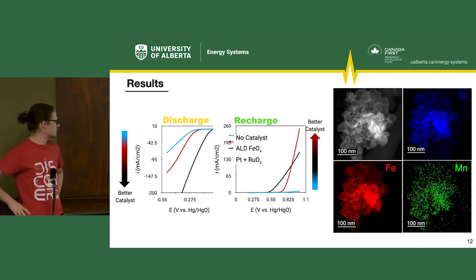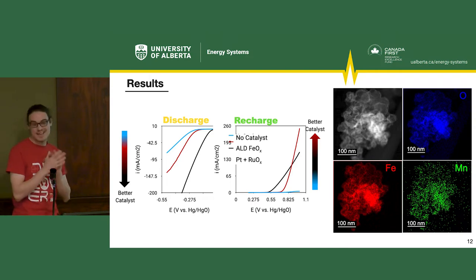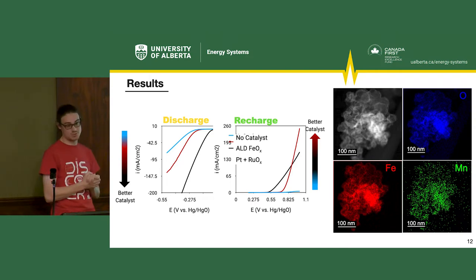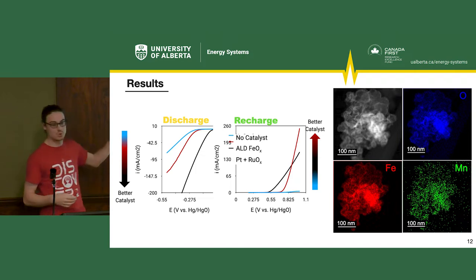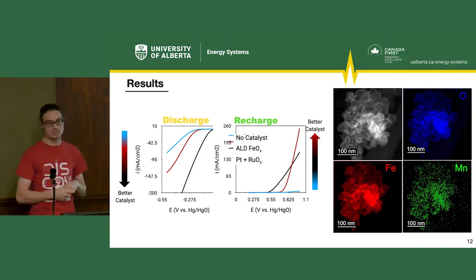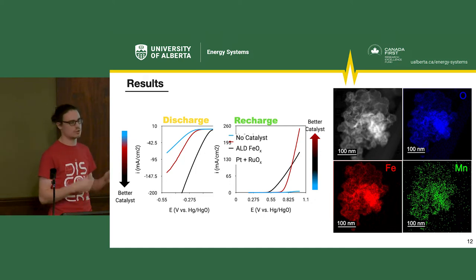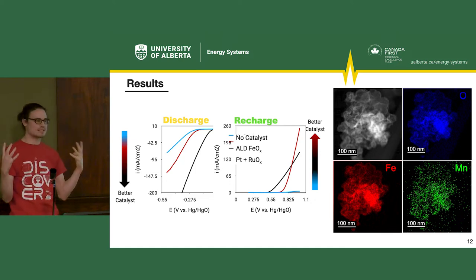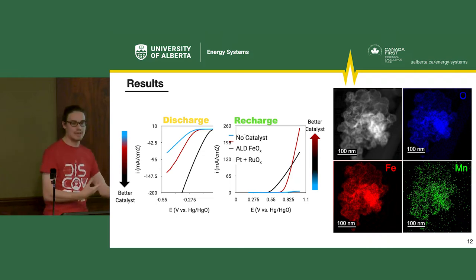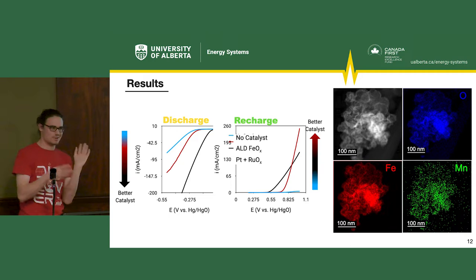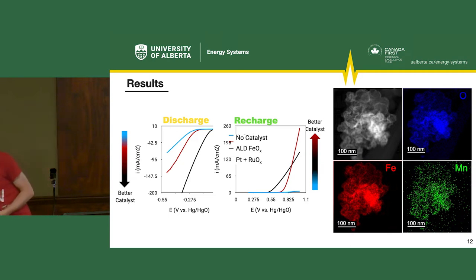So discharge could be improved. Well, it just so happens that the manganese oxide I'm using actually is a catalyst towards the discharge reaction. Somebody before me was doing their work on manganese oxide for the discharge only. So I thought, well, maybe I can get the best of both worlds by having more manganese or going back and forth between manganese and iron, right? Maybe make some sort of super cycle. And so that's exactly what I did.